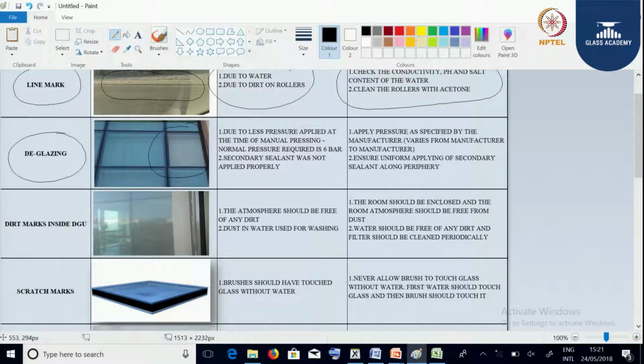Normal pressure required is 6 bar. Secondary sealant was not applied properly. We can overcome these issues by applying pressure as specified by the manufacturer, and ensuring uniform application of secondary sealant along the periphery of the glass.